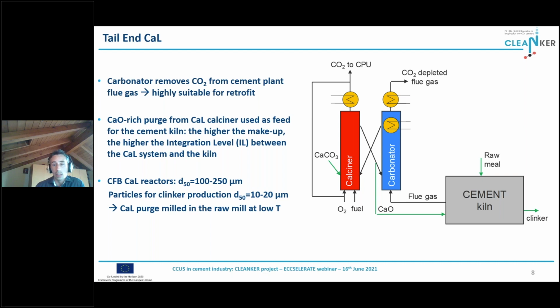In the tail end case, the configuration is simpler. The calcium looping CO2 capture process is placed downstream of the clinker burning line. So it is actually an end of pipe application where the carbonator treats all the flue gases exiting the cement kiln, all the flue gas arrows that I showed before. Again, also in this case, the calcium oxide rich purge produced by the calciner can be used as raw meal for feeding the cement kiln.